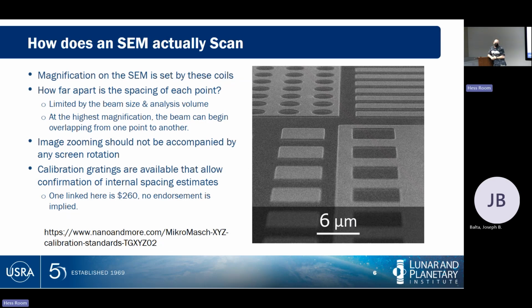If I was actually trying to figure out what this was, I think we actually cranked the accelerating voltage up to 20 just to make sure we could get them. And if I counted longer, it might have helped a little bit. But in reality, I couldn't actually answer this perfectly with the SEM. We had too many potential heavy elements, too many overlapping peaks. The sulfur peak, that was the K peak for sulfur, was overlapping with the L peaks for whatever else it was. There's a lead peak or two in there. And then beyond that, it's probably some mixture of stuff creating this set of peaks where it's gotten hard to identify. So it's probably some sort of a PGE, platinum group element rich nugget, and that's the best we could do. Which is kind of cool anyway.